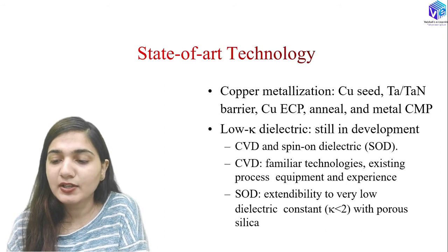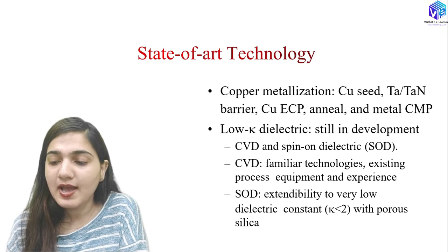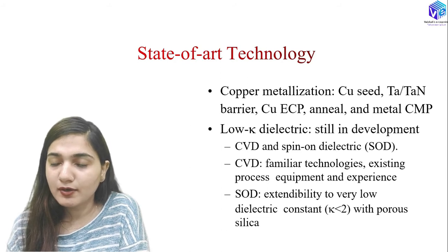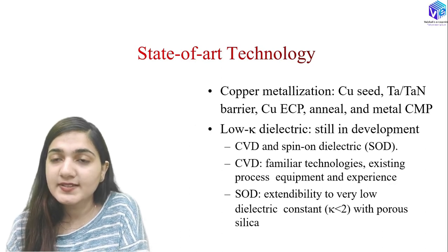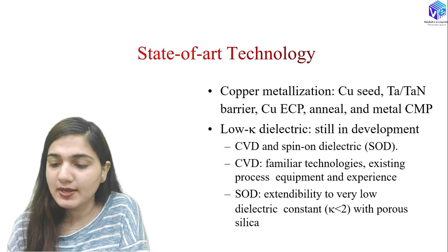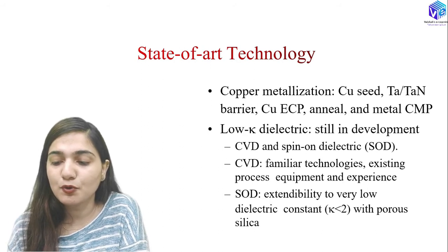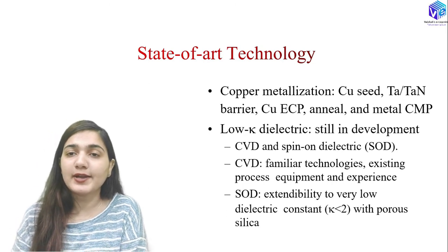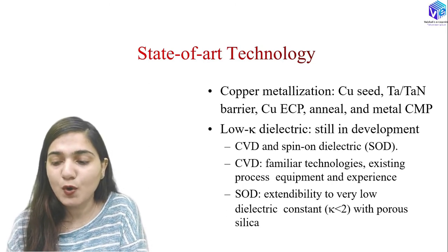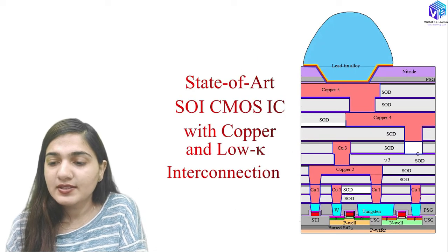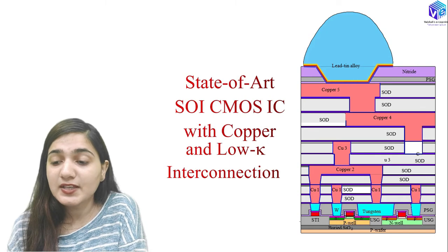The low dielectric constant dielectric is still in R&D. We can use CVD or spin-on dielectric (SOD). CVD is a familiar existing process with established equipment and expertise. SOD — spin-on dielectric — offers extendability to very low dielectric constants with porous silica. Whenever a dielectric with a very low dielectric constant is needed, SOD is preferred.